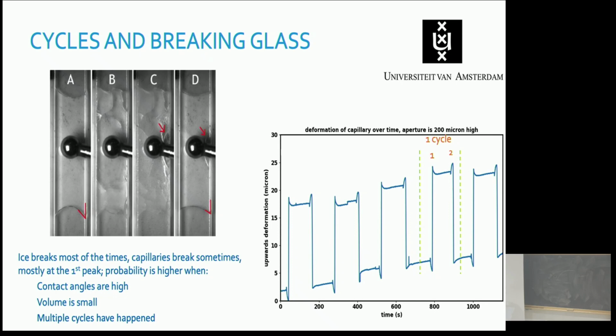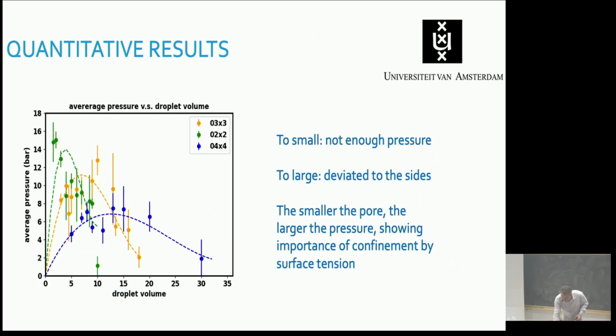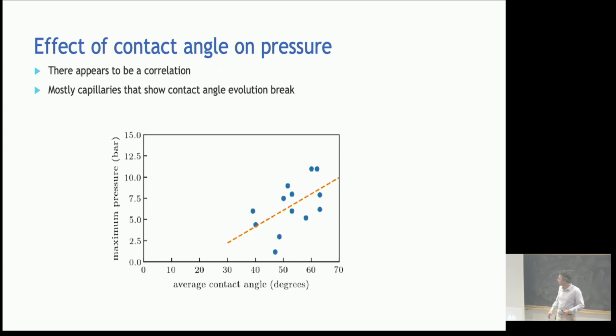Yes, so this is really the effect of cycling. At each cycle, we get a higher pressure, and at some point, the capillary breaks, and the experiment is over. And so we think that is due to the contact angle evolution. We did a lot of experiments. Rosa did a lot of experiments, and it's a bit noisy, but I hope you will agree with me that when the contact angle increases, the pressure also increases. And so that explains the effect of the cycling.